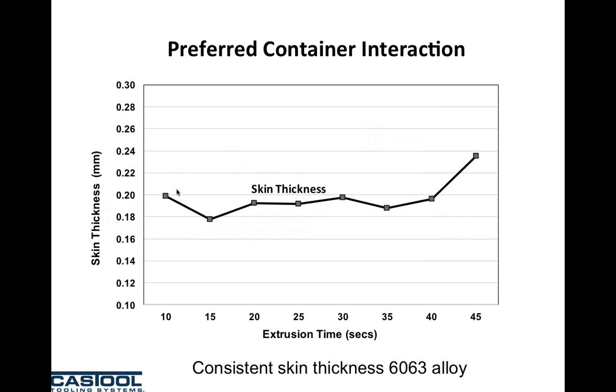The graph just shows that we did a simulation study on 6063 alloy. It's in metric, so that's about 8 thou for the aluminum skin. So you can see the aluminum skin is quite consistent from start of push, 10 seconds, to the end of the push, 45 seconds. So that's what we want, to have a consistent aluminum skin. And that tells you the bore is concentric, round, and straight. The liner is stable. There's no alignment problem or issue between container and dummy block as well.